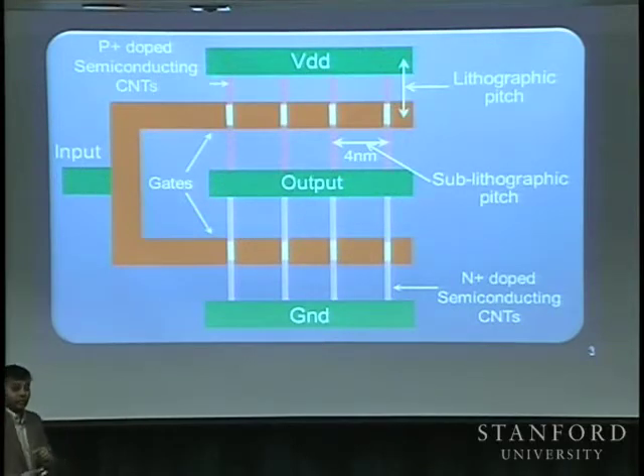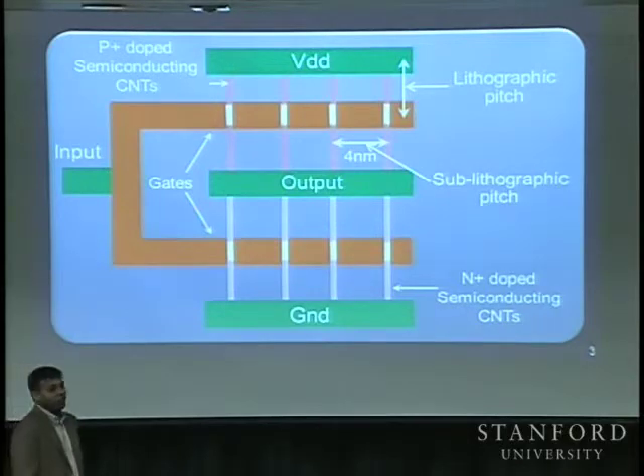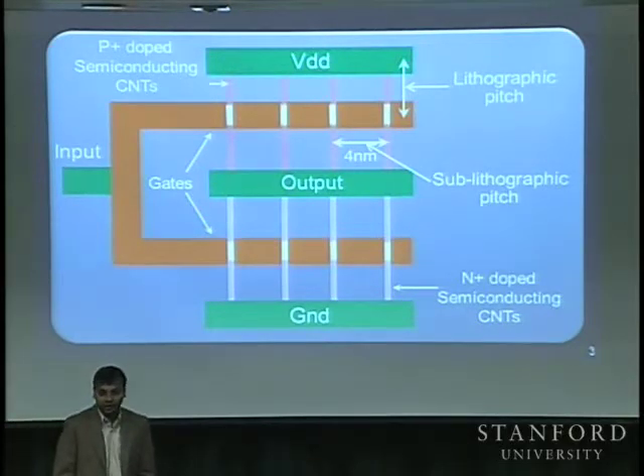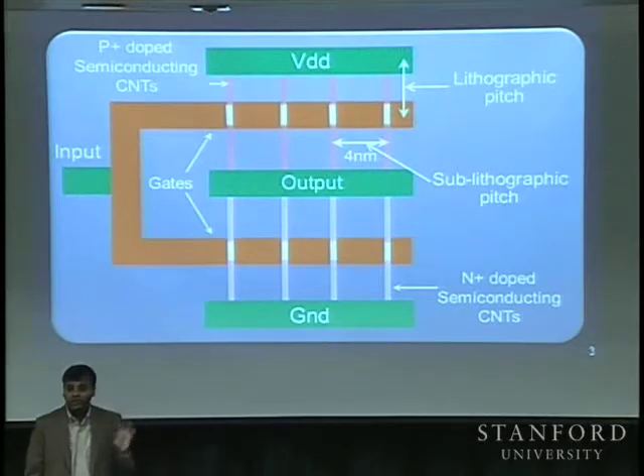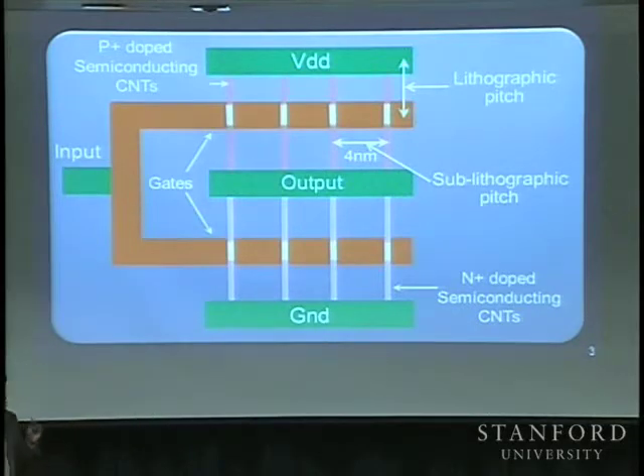So if you could achieve very dense arrays of carbon nanotubes, which is a very difficult goal right now, you should be able to get somewhere around a spacing of 4 nanometers, which would mean roughly around 250 carbon nanotubes per micron. And I will come back to this density issue later on, but this is a very important issue.